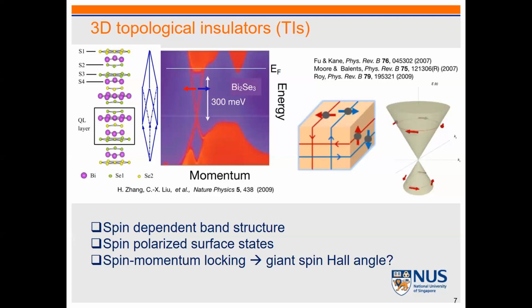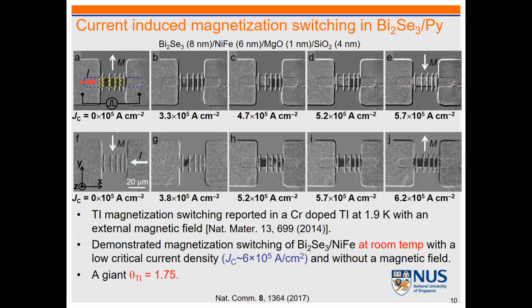So that excited many groups' attention, including my group. Eventually, after certain optimization, we found about 8 nanometers is a good thickness to compromise between the spin Hall angle and the resistivity. Not so resistive, and the spin Hall angle is also reasonably big.